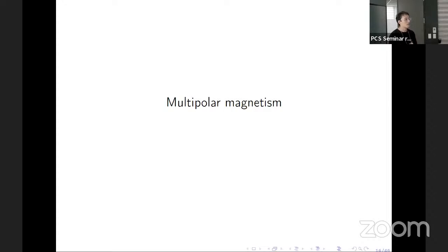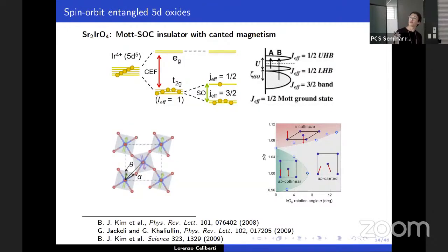Can you go two slides back, please? That's for me to understand. So the spin-orbit coupling in this upper example, this Mott SOC insulator, what does it do mainly? Is it reducing the density of states at the Fermi energy, removing some of these degeneracies, and then you need less interaction to open the gap? Yes, basically, yes. As you can see from this splitting you have here, you have just a degeneracy of 2, and then this band is split by the Coulomb interaction.